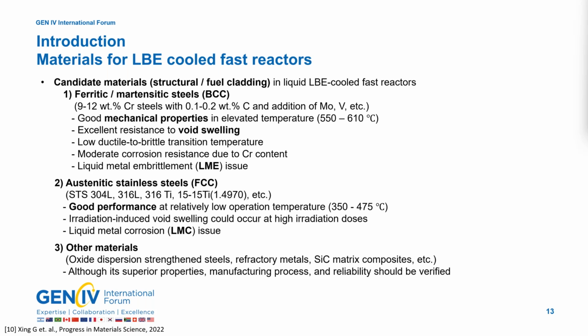There are several candidate materials for structure and fuel cladding in liquid LBE-cooled reactors. Firstly, there are ferritic martensitic steels that have BCC crystal structure. The material has good mechanical properties at elevated temperatures, excellent resistance to void swelling, low ductile to brittle transition temperature, and moderate corrosion resistance due to chromium contents. However, it is reported to be susceptible to liquid metal embrittlement.